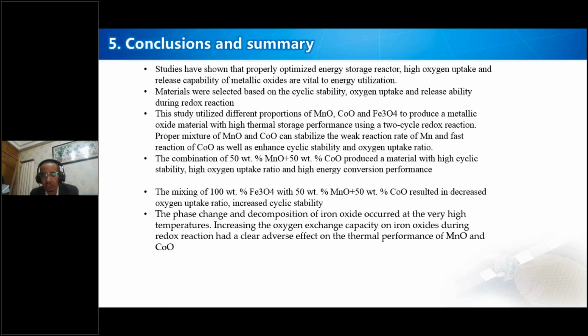So, in conclusion and summary, this study has shown that for proper optimization of an energy storage reactor, high oxygen uptake and release capability of metallic oxides are vital to energy utilization. Materials were selected based on cyclic stability and oxygen uptake during redox reaction. This study utilized different proportions of manganese oxide, cobalt oxide, and iron oxide to produce metallic oxide material with high thermal energy performance in cyclic redox reaction. A proper mixture of manganese oxide and cobalt oxide can stabilize the weak reaction rate of manganese and the fast reaction of cobalt oxide, as well as enhance cyclic stability and oxygen uptake ratio.